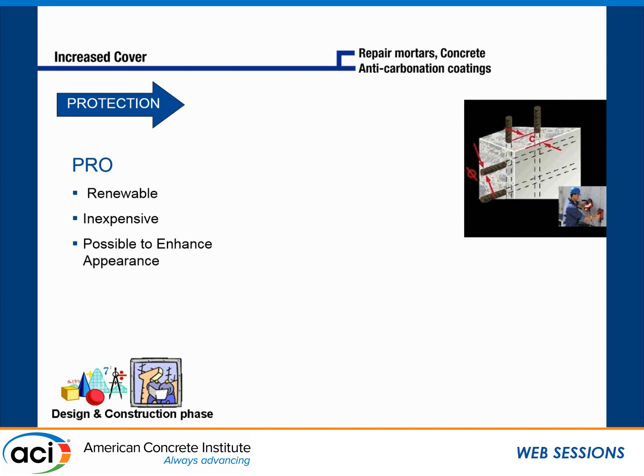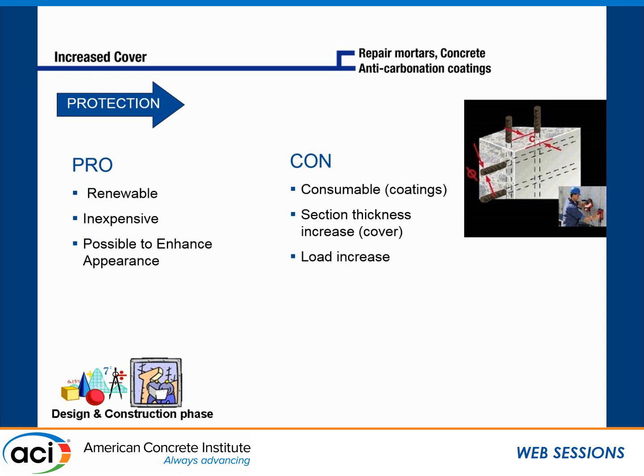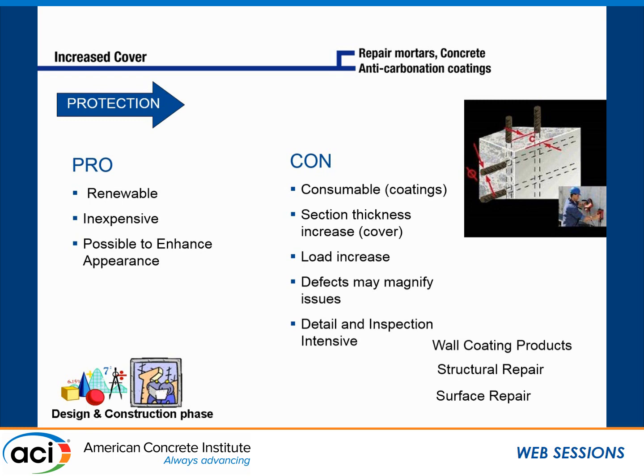Increase cover. Make the concrete thicker. It's renewable. I can always make it thicker if I can take the dead load. It's inexpensive, and it's possible to enhance the appearance, such as with an anti-carbonation coating, for example. I paint the wall. Downsides, they're consumable. It doesn't last forever, such as for coatings. I do increase section thickness, I can increase the load. If I have defects in my protective system, I can actually make the problem worse. And it's detail and inspection intensive. Examples of this: wall coating products, structural repair, surface repair.